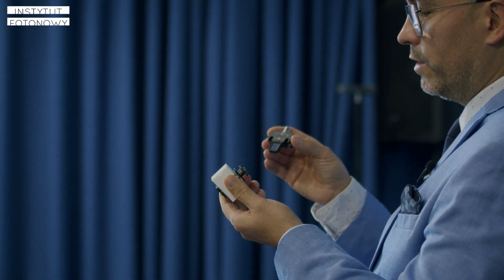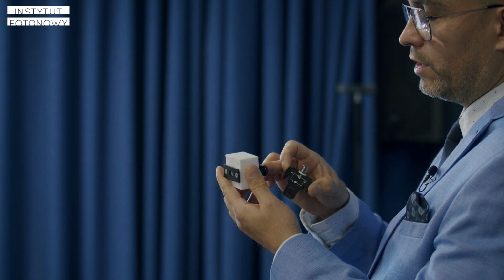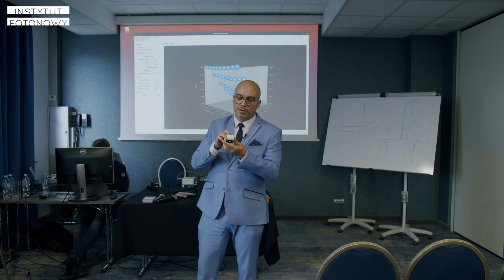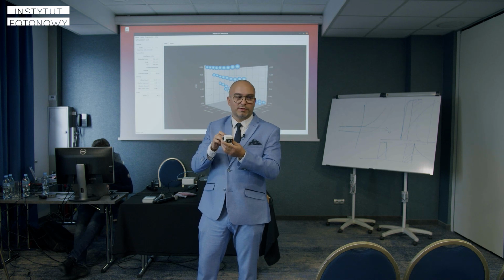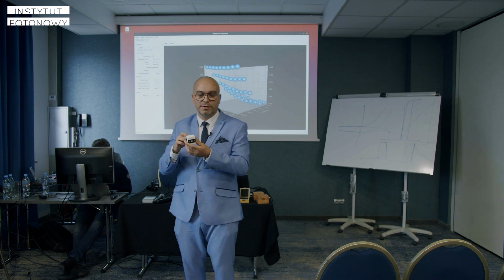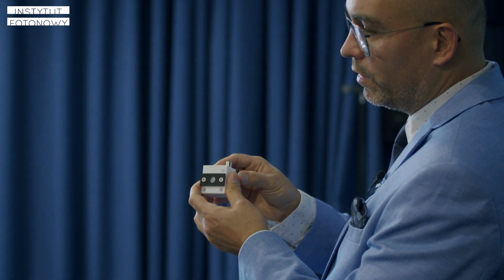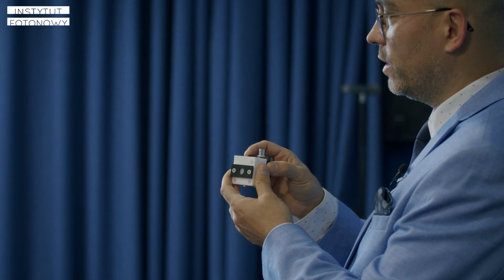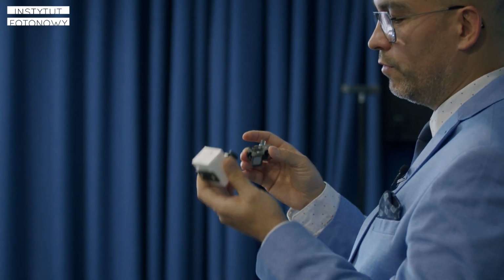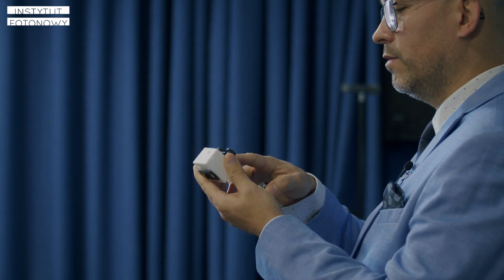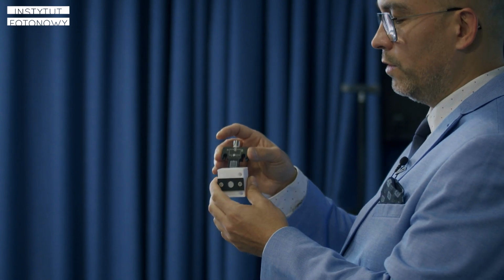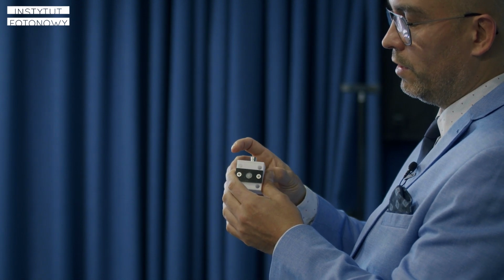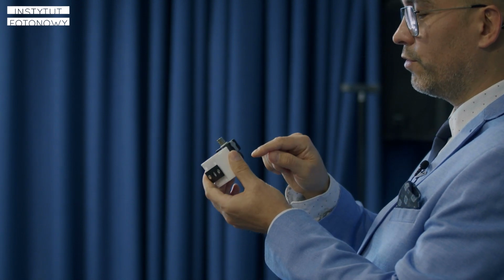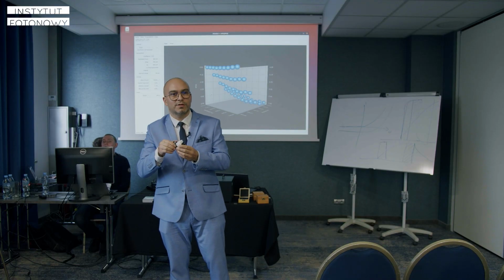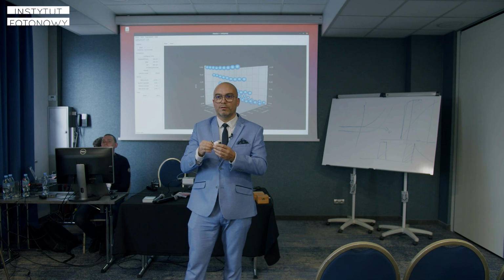We make one measurement with a glass window, which we assume has 100% transparency, with some error. So we measure how much light is delivered to the sample. Then we can place the sample in our cuvette, which is less transparent, and we repeat the measurement of the light going through the sample. We can subtract these two values, and the difference is the amount of light which is absorbed in the sample.